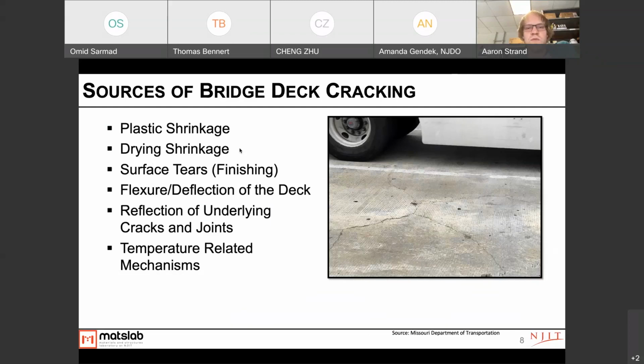Sources of cracks that we see in our bridge decks are typically plastic shrinkage, drying shrinkage, surface tears, typically from finishing, flexure and deflection of the deck from loads, reflective cracking from underlying cracks or joints, typically seen in overlays, and also temperature-related mechanisms. These cracking mechanisms are important because some of them, like plastic and drying shrinkage and surface tears, can be present from basically day one on our bridges.